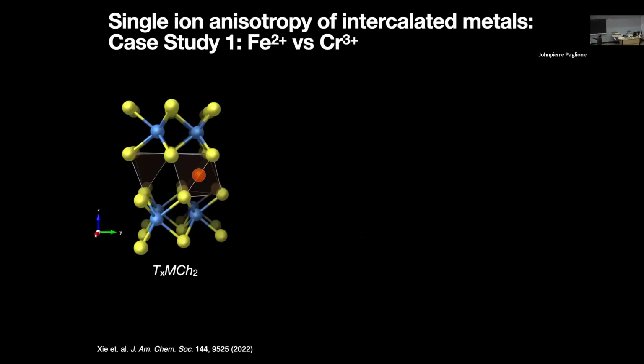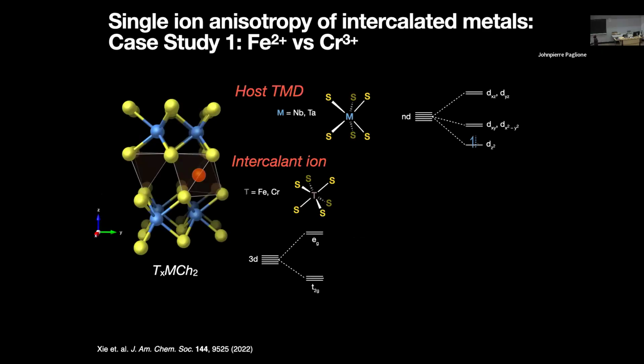So if we have some transition metal intercalated TMD, as I said, in nearly all cases except for the group 4 cases, like zirconium and hafnium, the intercalant is going into the octahedral interstitial site. We can think of it as starting out with the transition metal atom, and then the transition metal transfers electrons to the host lattice. So it's going to end up being usually divalent or trivalent. Divalent for, say, iron and cobalt, trivalent for vanadium and chromium.